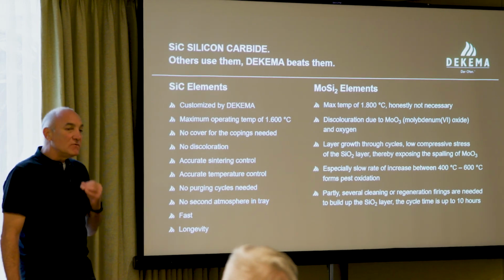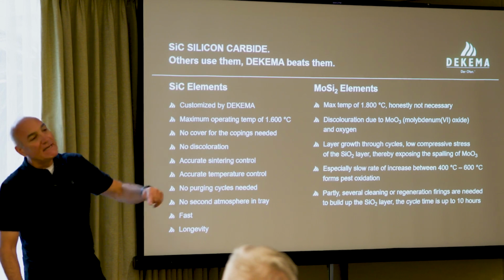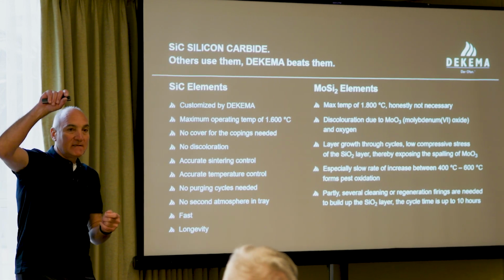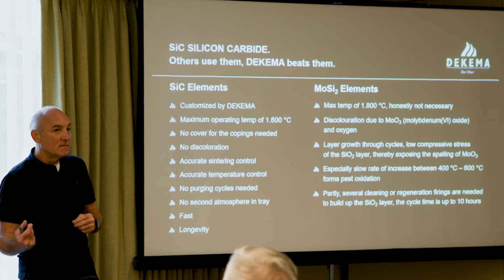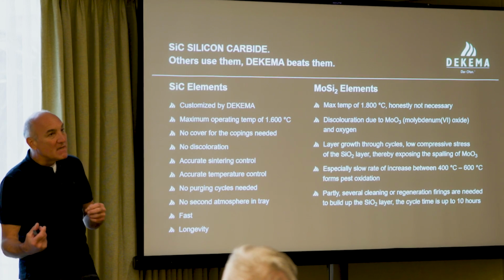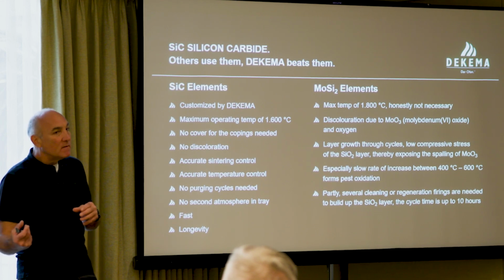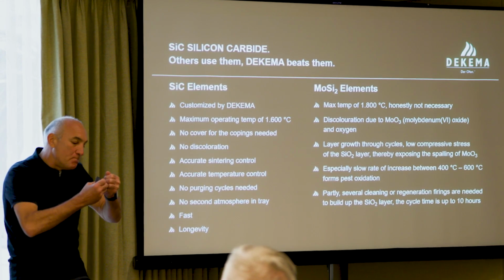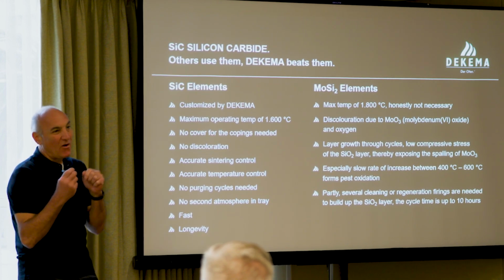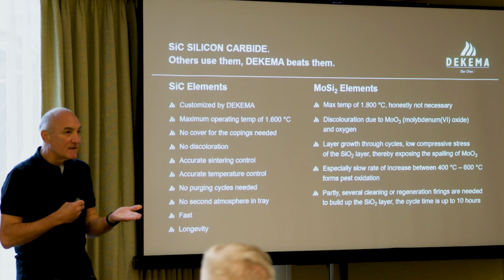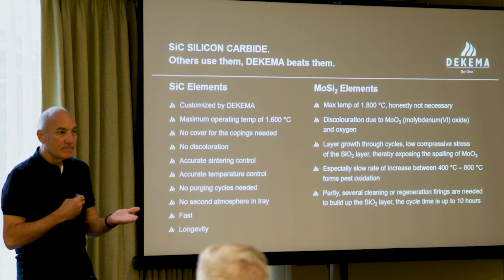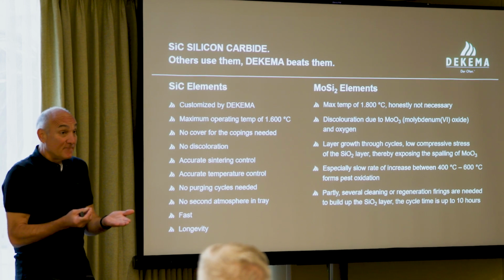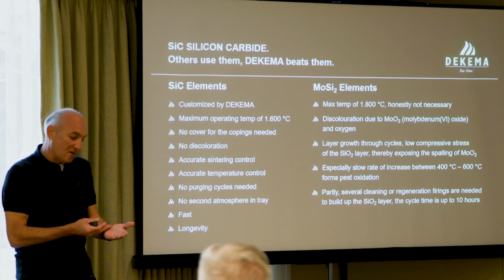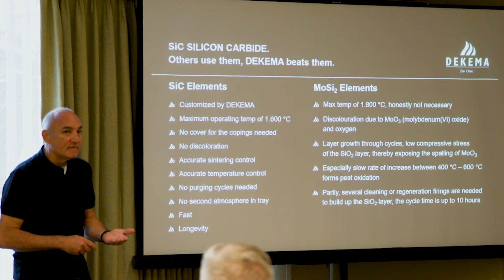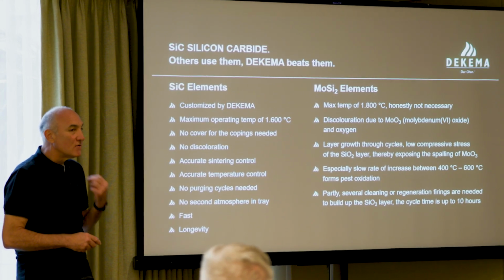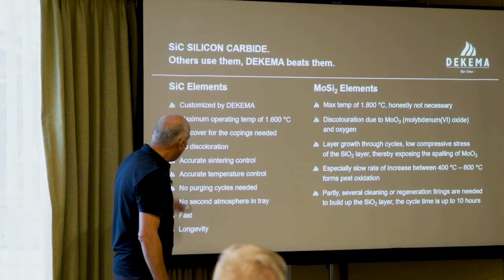Purging cycles with MoSi furnaces is nothing else than recreating a glass layer on the molybdenum disilicide, so you don't have any more greening effects. What you surely should do maybe after 2 months and then weekly, in a 10-hour cycle, because the glass layer has to build up again slowly. How long does it last? Nobody knows. You know it when you have the next green zirconia. Just let technicians get used to it. Oh, it's not the right color, I put whatever color on it. But this is not good, it's not real. So no purging cycles needed.